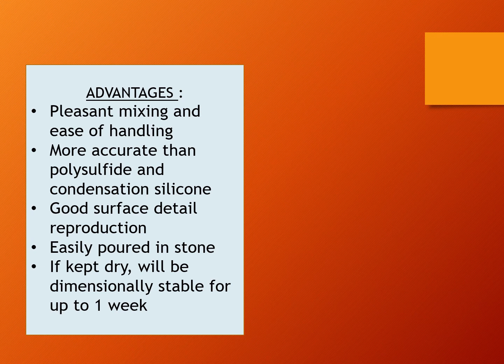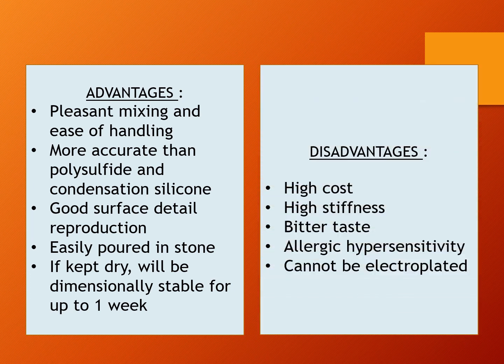Coming to the advantages and disadvantages, advantages include pleasant mixing and ease of handling. It's more accurate than polysulfide and condensation silicone, good surface detail reproduction, easily poured in stone, and if kept dry, it will be dimensionally stable for up to 1 week. The disadvantages include high cost, high stiffness, bitter taste, allergic hypersensitivity. 0.5% of patients exposed to polyether showed allergic reaction due to the aromatic sulfonate catalyst, and this cannot be electroplated.